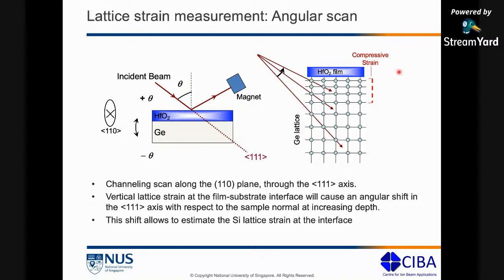So what happens is, when you have this amorphous film on a single crystal lattice, right at the interface there will be some amount of strain in the crystalline lattice. Why this strain comes is because you're going to have a lattice mismatch. Hafnium and oxygen have different atomic sizes compared to germanium.